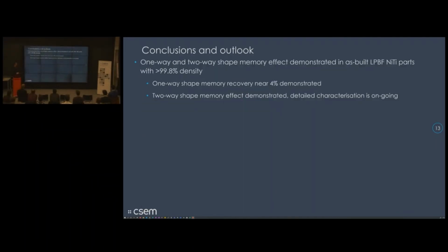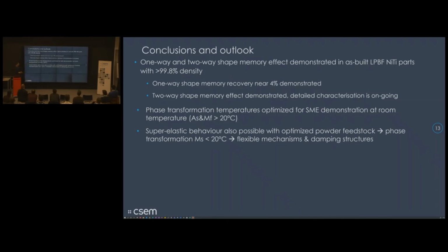So in conclusions and outlook, one-way shape memory and two-way shape memory effect were demonstrated in as-built laser powder bed fusion nickel titanium parts with more than 99.8% density. One-way shape memory recovery was near 4%, and two-way shape memory effect was also demonstrated, and detailed characterization is ongoing. The phase transformation temperatures were optimized for shape memory effect demonstration at room temperature, with austenite start and martensite finish temperatures above 20 degrees. And of course, also superelastic behavior is possible with optimized powder feedstock.